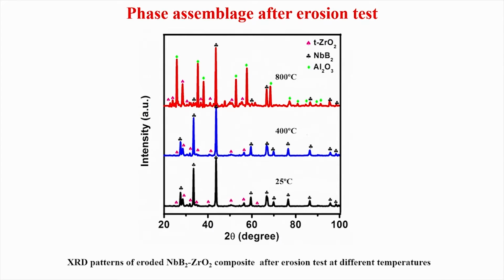Now, in terms of the phase assemblage after the erosion test, this is the niobium boride material, and you can see at 400 degrees Celsius very clear niobium boride peaks, and there is no niobium oxide peak. So, niobium boride is extremely resistant to oxidation. At 800 degrees Celsius you will see a lot of alumina particles, completely embedded on or covering the surfaces. Perhaps at higher temperature these alumina particles are almost welded on the material surfaces, and that is why you get this alumina peak very strong. And the tetragonal zirconia peak is present in the spark plasma sintered materials, and that comes from the milling media in these particular cases.